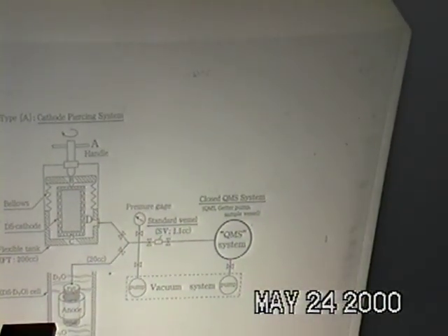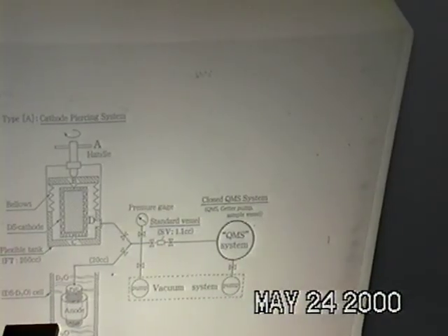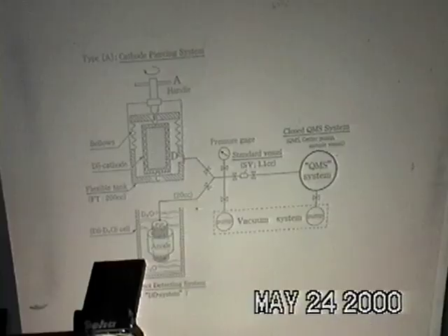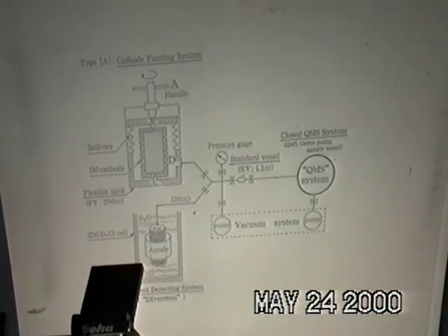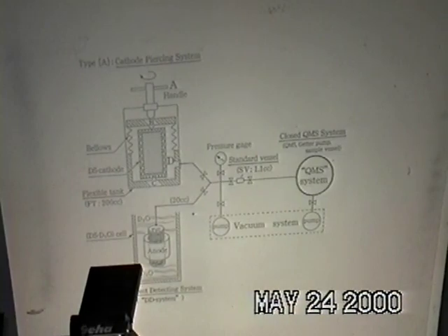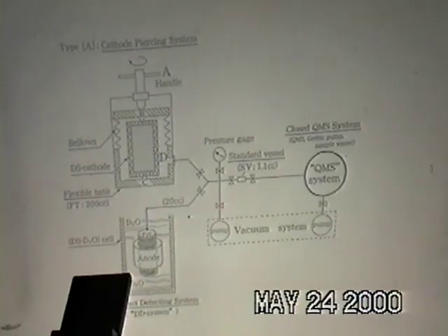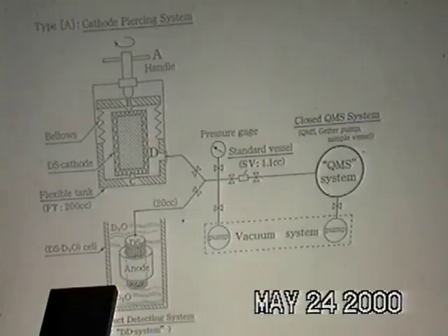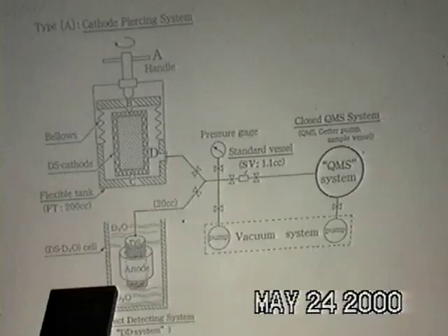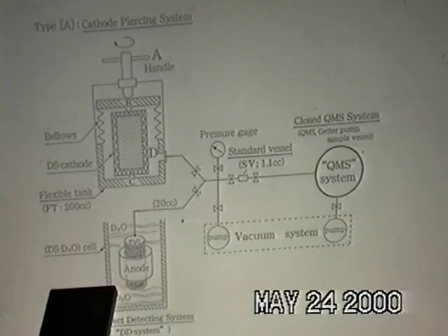In all these experiments, we measured helium released from only palladium black after long-time evacuation to 10 to minus 9 torr and heating, but did not measure the inner gases inside the cathode. We therefore developed a new detection system, as shown in this diagram, and last year finally succeeded in capturing inner gases inside this cathode, including the palladium black. The amount of all detected helium was over 100 times larger than that released from palladium black.